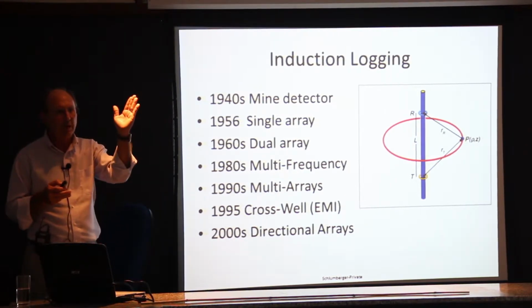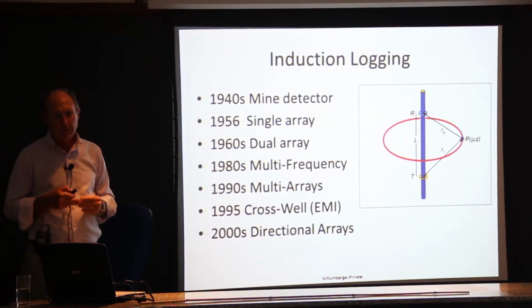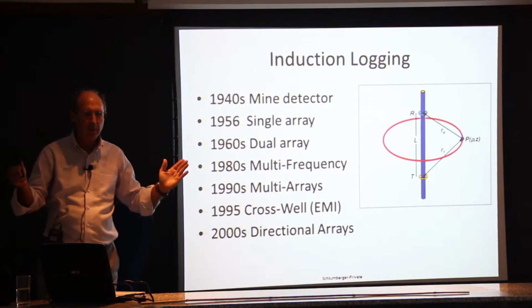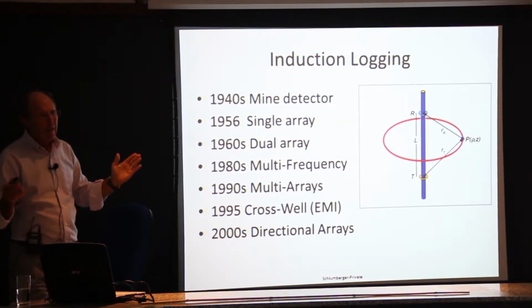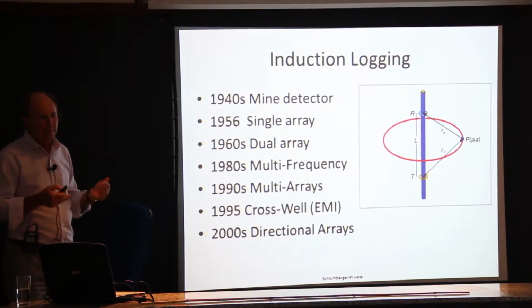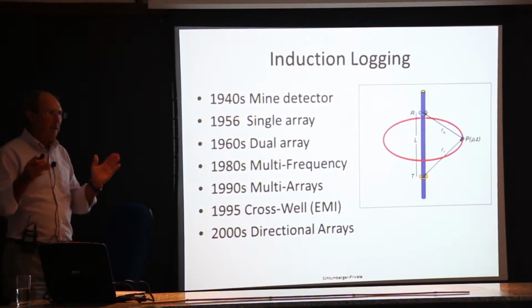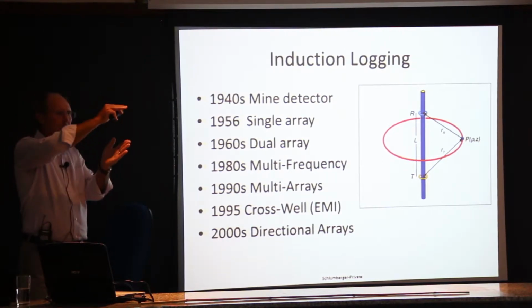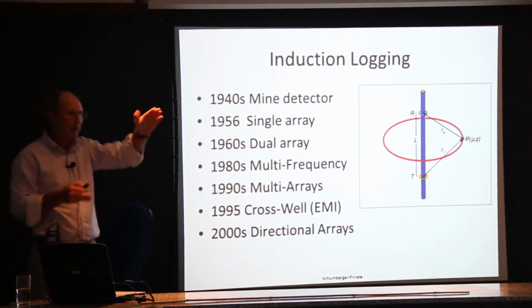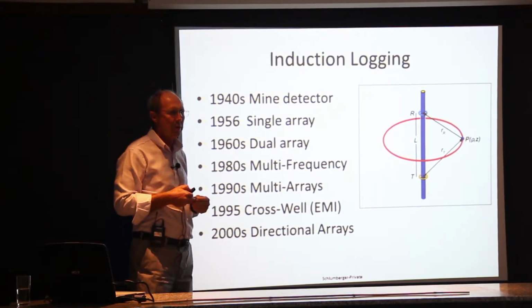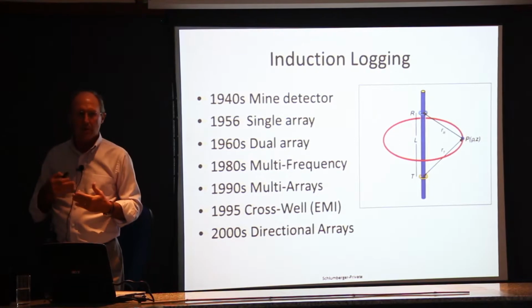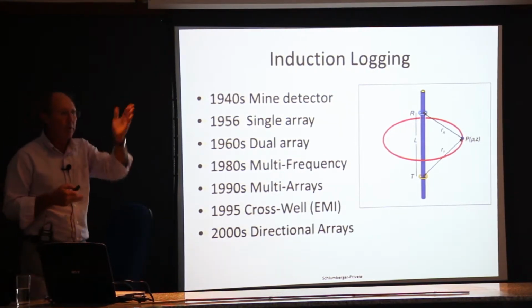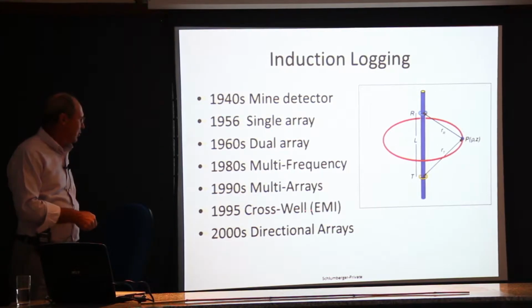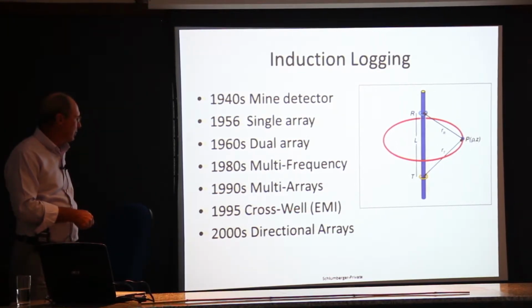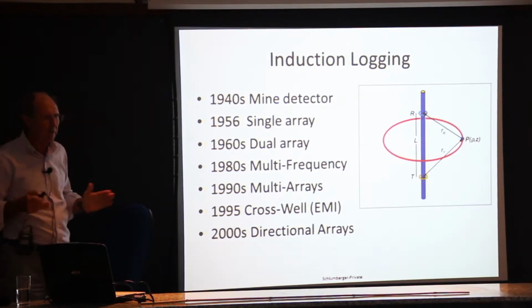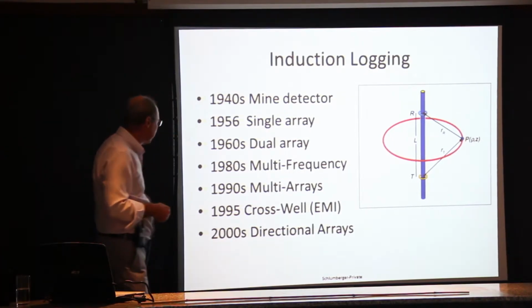You can see the water flood coming, but there's logistics problems with accessing 2 wells at the same time. And eventually, companies like Aramco, etc., they felt they could see the flood, but they couldn't really tell enough about the shape of it. Was it convex? Was it concave, etc.? They wanted to know this additional information, because that told them extra information about the wettability and recovery factor of the formations you're sweeping. So this is not used near as much as we hoped it would be, mostly because of the resolution and the logistics of getting access to do 2 boreholes at the same time.